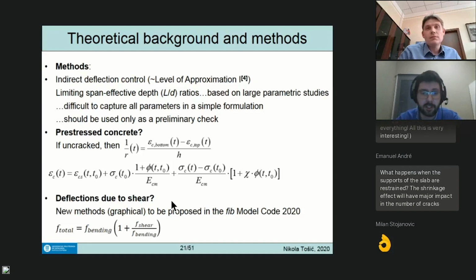There are parts in the code, which I'm not going to cover in detail here, concerning pre-stressed concrete, which is going to be much more simple. If it's uncracked, then the curvature is just the bottom and top strain divided by the overall depth. Here we see the relationship of the concrete strain: the shrinkage strains, the strain from pre-stressing, and the creep coefficient at the time of pre-stressing. Then you have the increment of stress up to the time you're looking at, but you're using the same creep coefficient with the aging coefficient, which is generally 0.8 or 0.9.